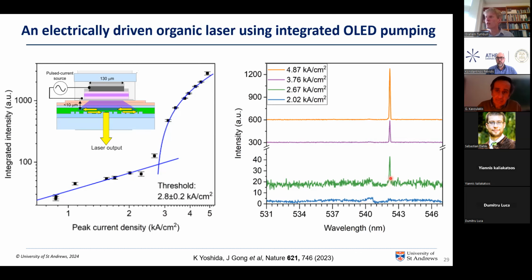Above threshold, we find that this laser peak rises up. Typically, it's 0.1 nanometers wide, limited by the resolution of our spectrograph, and so that's typical for these pulsed lasers. We could probably work harder to narrow it further, but that's not something we've tried to do.